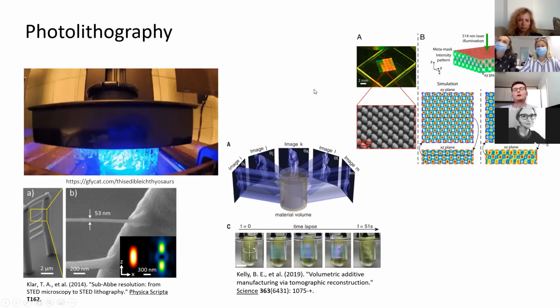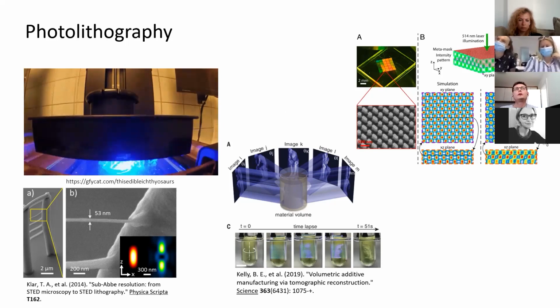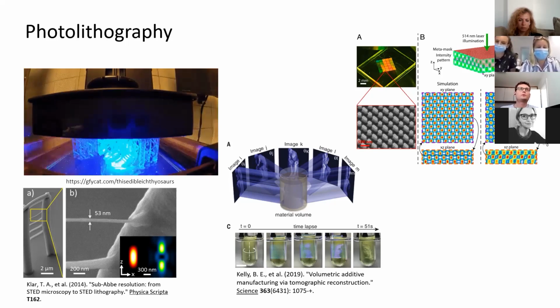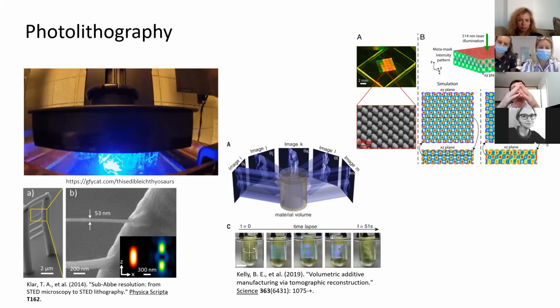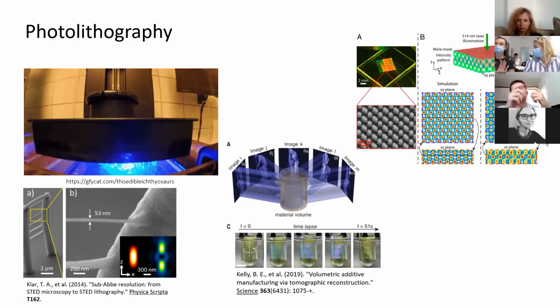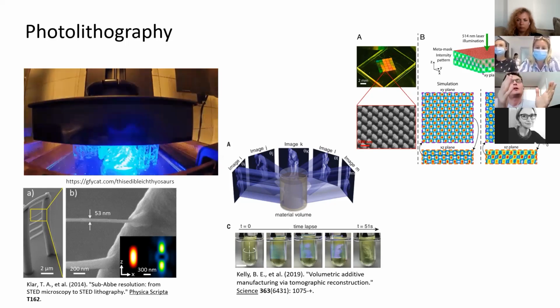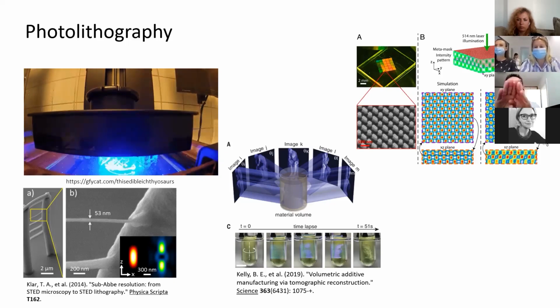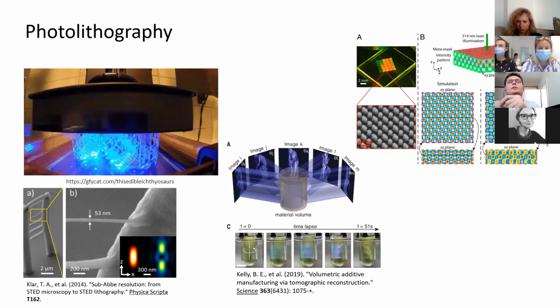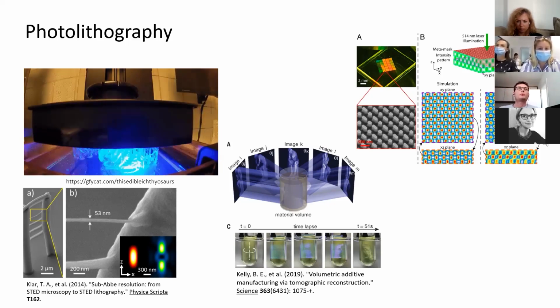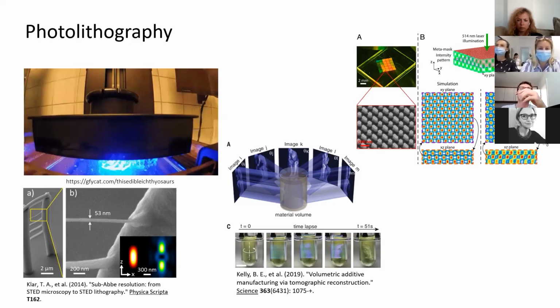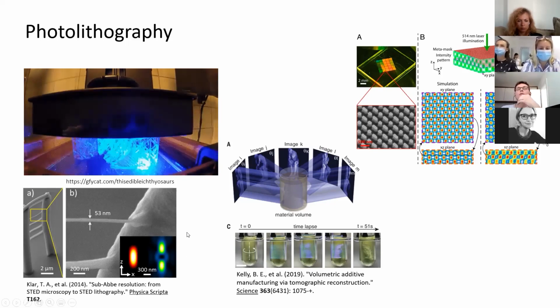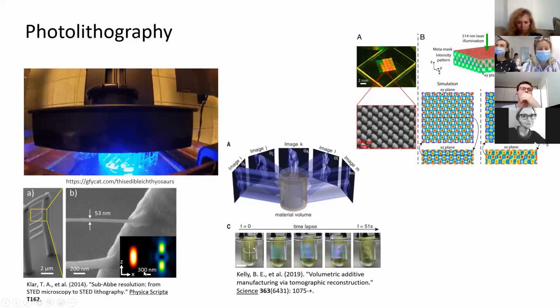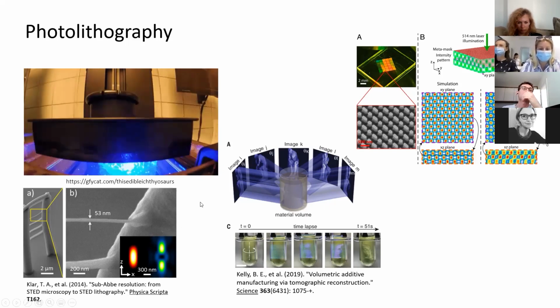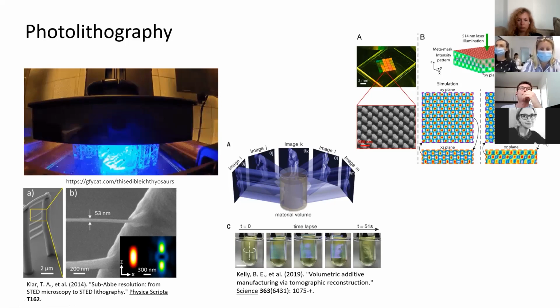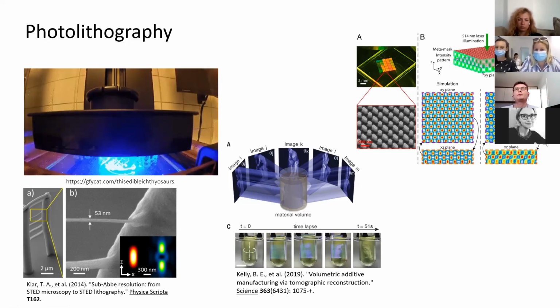But if you exploit multi-photon or two-photon lithography, which is in principle similar to multi-photon fluorescence, if you're familiar with that, you have a reaction only at the focal point of the laser beam. You have a laser with a longer wavelength, and in the focus the photons add up as if you had a photon with the appropriate wavelength to start the reaction, and you get really fine resolution through that. So here you can go into submicron resolution. If you look at this image by Klar et al, you even get below 100 nanometers of precision, which is really impressive.